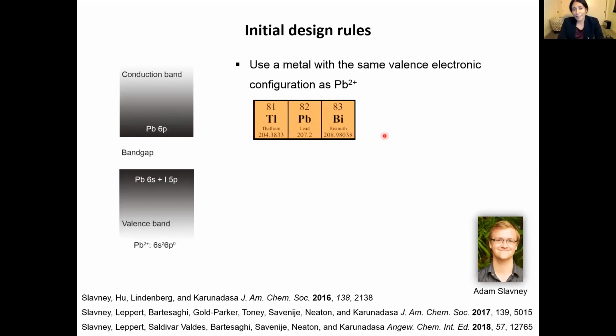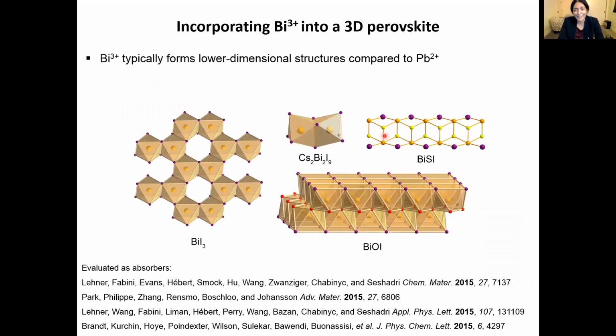So as a first step, we decided to take bismuth 3+ and see whether we can incorporate it into a perovskite. Except that bismuth doesn't want to go into a perovskite. Bismuth is 3+, lead is 2+, and 3+ ions prefer different coordination environments and different connectivity. So it turns out that bismuth prefers low-dimensional structures. So we needed to be clever about persuading bismuth to go into a perovskite lattice.